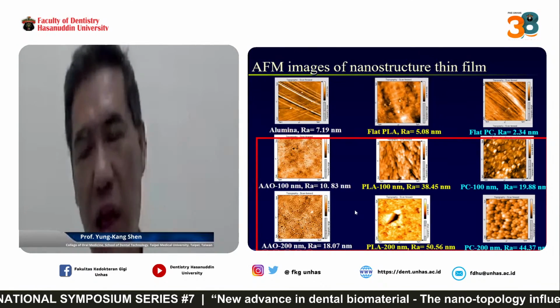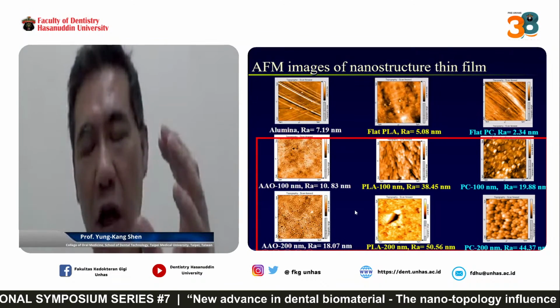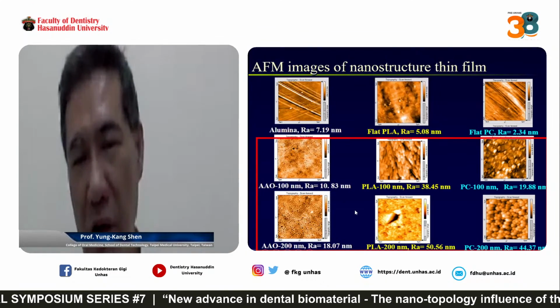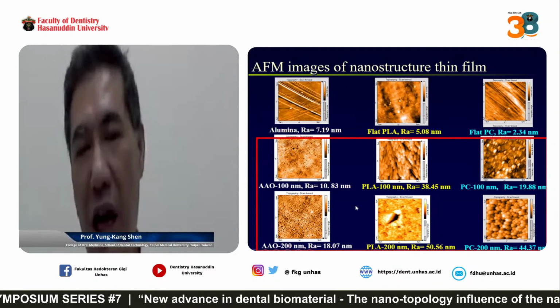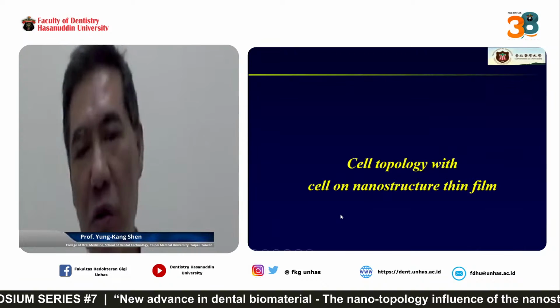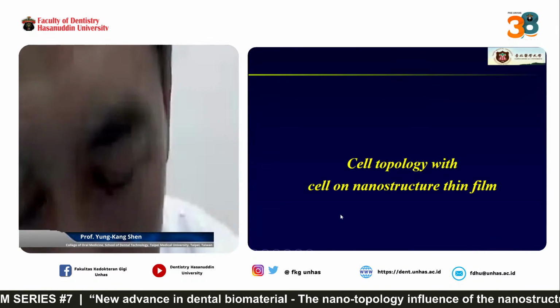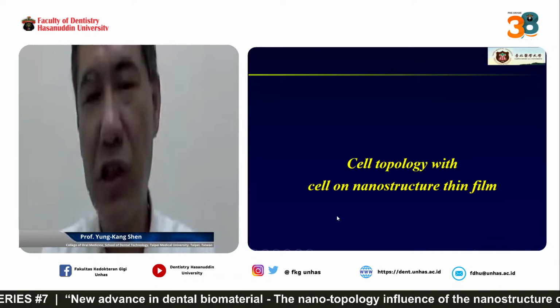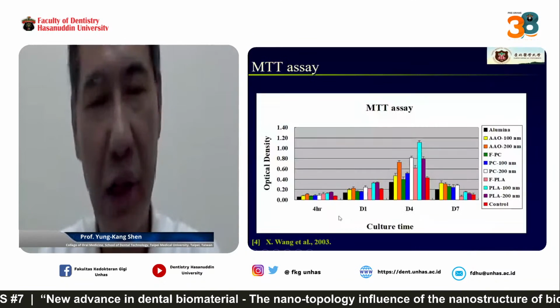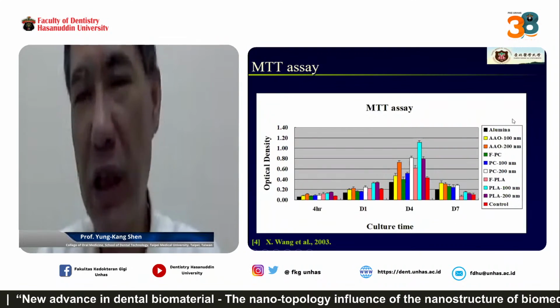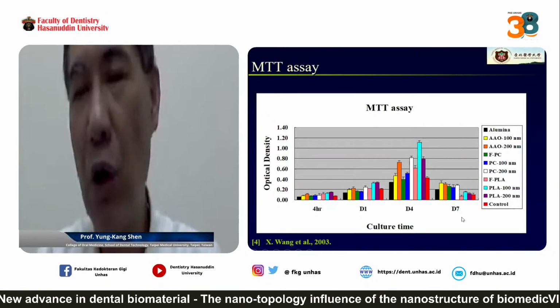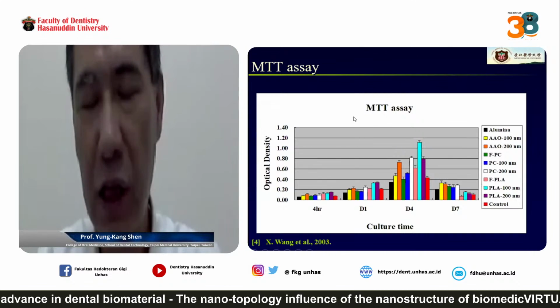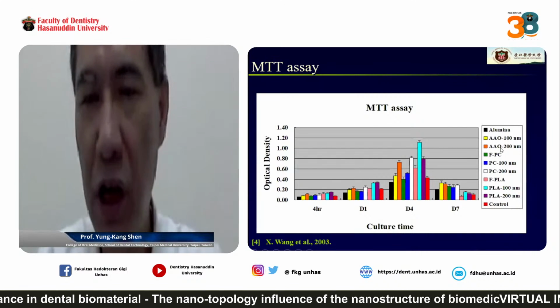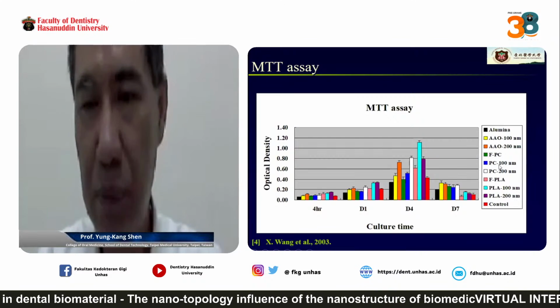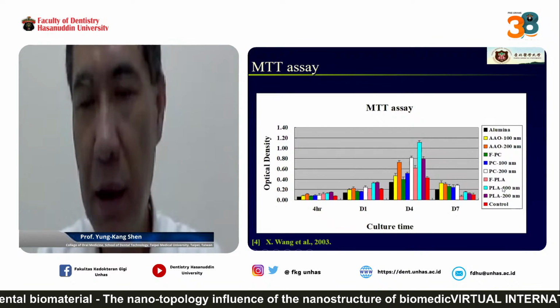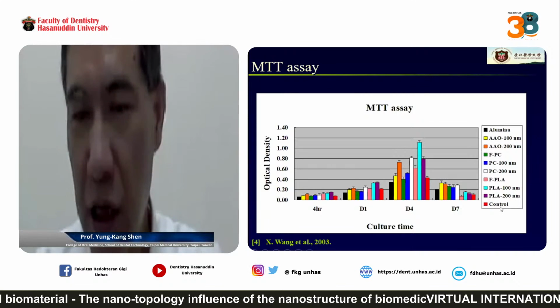So here, I can say again, the thin film with the nanostructure on its surface can get a larger surface roughness. Now I think in Hasanuddin University, the listeners will have interest in cell topology with the cell on nanostructure thin film. Here, we do so many experiments. The alumina is the pure alumina tablet. You can see we do so many cell culture MTT assays for AAO-100 nanometer, AAO-200 nanometer, flat PC, PC 100, 200, flat PLA, PLA 100, 200, and the control group.